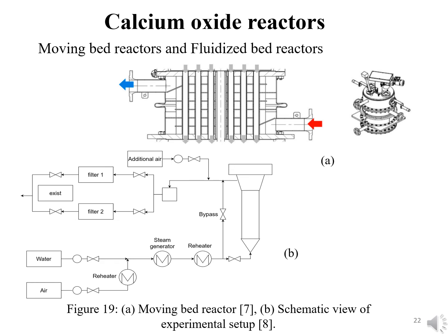Fluidized bed reactor. Researchers designed a fluid bed reactor and developed a model to predict the reaction process to solve the limitation of a fixed bed heat and mass transfer. The results demonstrate that the response rate has increased considerably. The researcher performed hydration and dehydration tests in a 5.5 kW fluidized bed reactor and developed a model to validate the results. Figure 19b depicts the experimental apparatus.